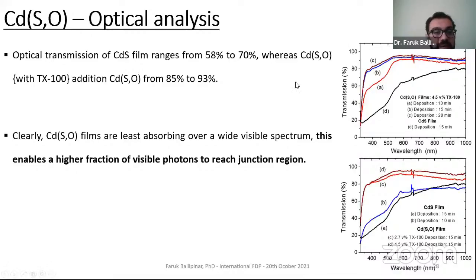So basically, in the optical transmission range, there is a significant increment. In the common CdS, in this region, it is 70%. In the cadmium oxysulfide, it reached 90%. So through this improvement, we expected cadmium oxysulfide films to have higher transmission and less absorption over the visible spectrum. Through this advantage, a higher number of visible photons reach the p-type, and this might help the efficiency increment.